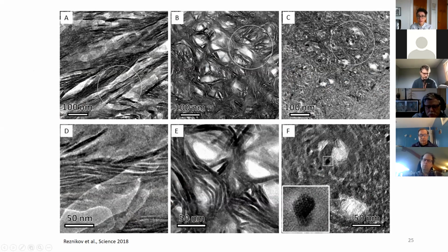observing them, all of a sudden, I managed to see, instead of 2 projections of mineralized collagen fibrils, 3. And depending on how you view the orientation of mineral and collagen in bone, it appears in 3 different fashions. When the fibrils are oriented more or less with the plane of the image, they look like wavy formations, like braided hair, with a certain curvature with a radius of around 200 nanometers, separated from each other by uniform repetitive gaps of around 1.5 nanometer or so.